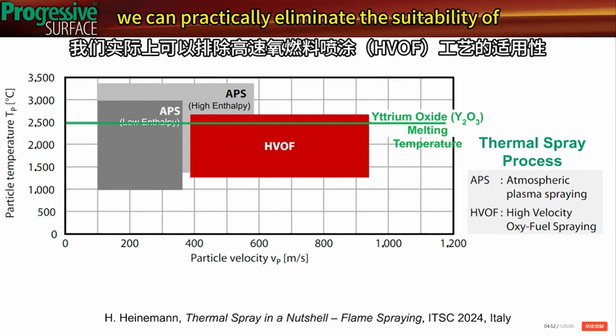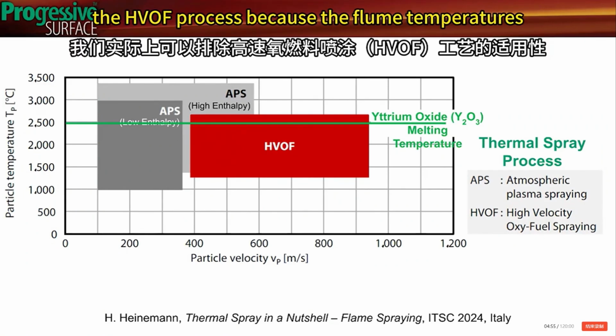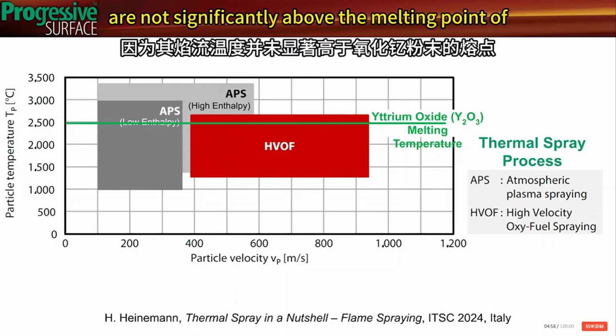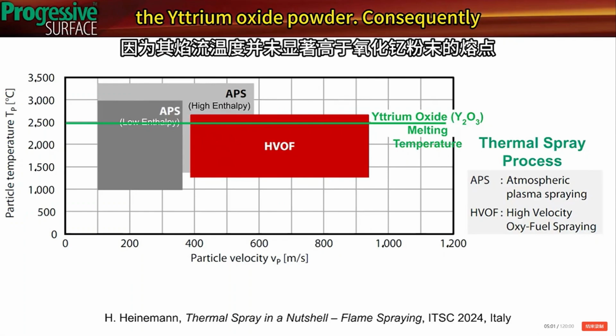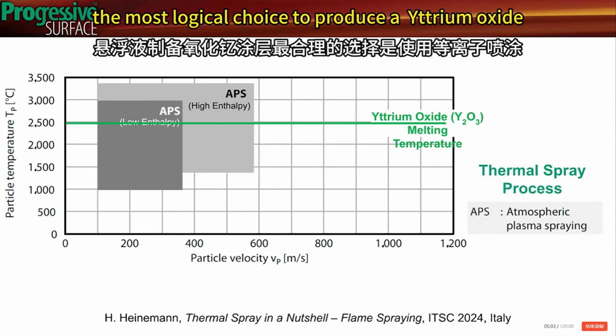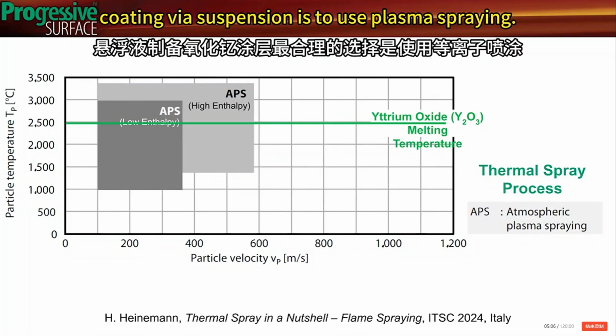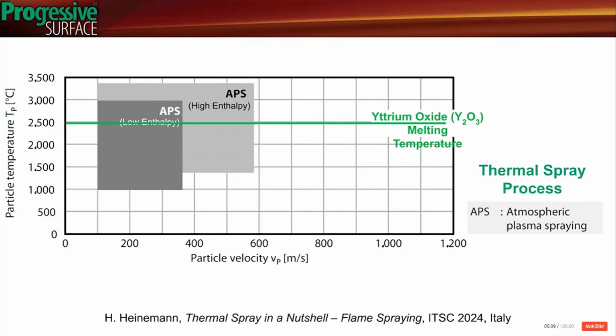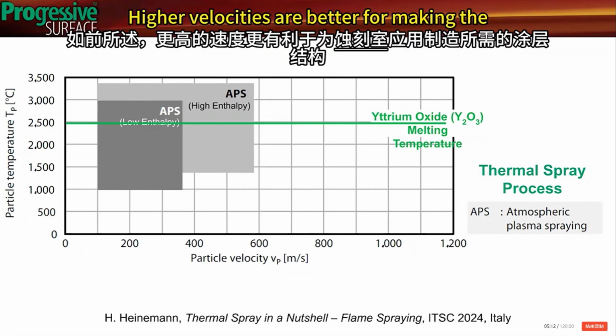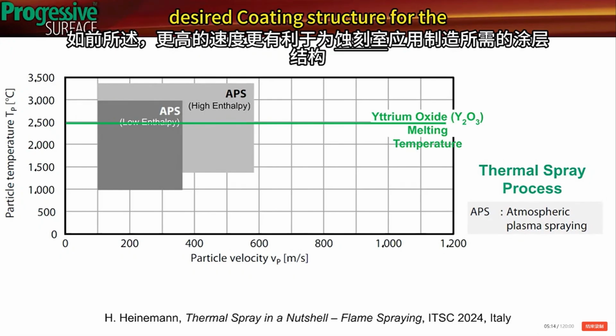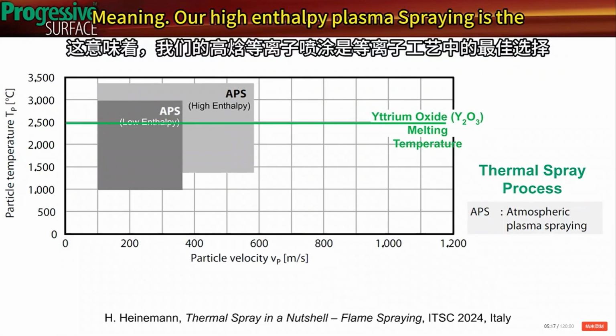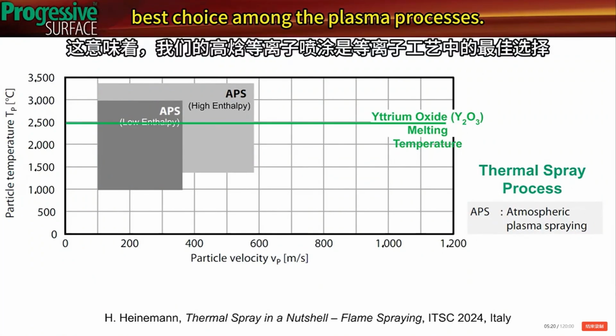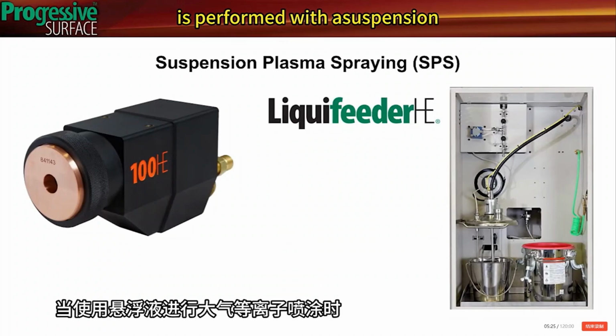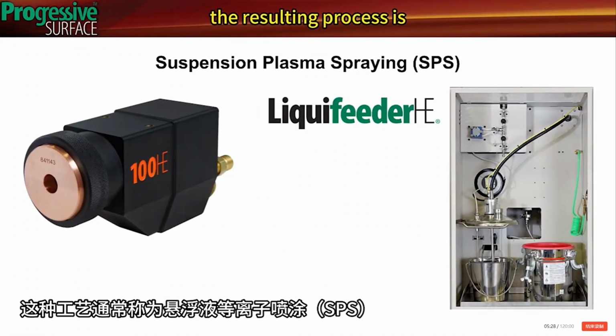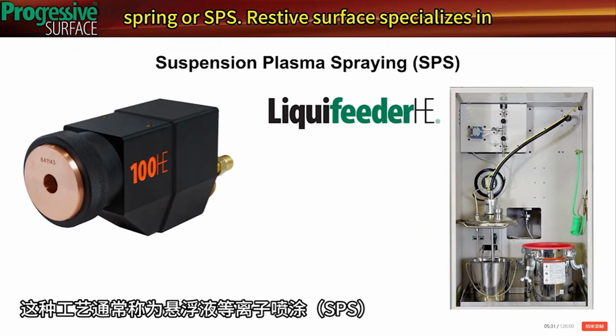With this reasoning, we can practically eliminate the suitability of the HVOF process because the plume temperatures are not significantly above the melting point of the yttrium oxide powder. Consequently, the most logical choice to produce a yttrium oxide coating via suspension is to use plasma spraying. As previously established, higher velocities are better for making the desired coating structure for the etch chamber application, meaning high enthalpy plasma spraying is the best choice among the plasma processes. When atmospheric plasma spraying is performed with a suspension, the resulting process is commonly termed suspension plasma spraying, or SPS.